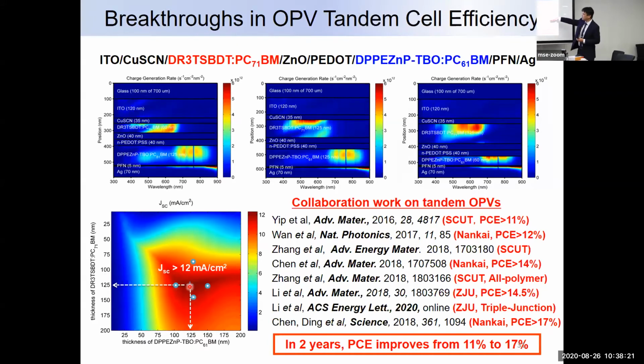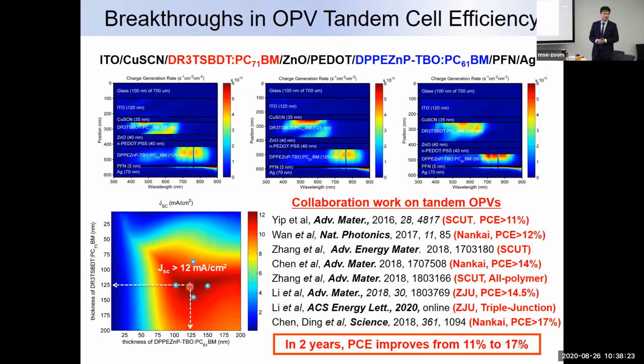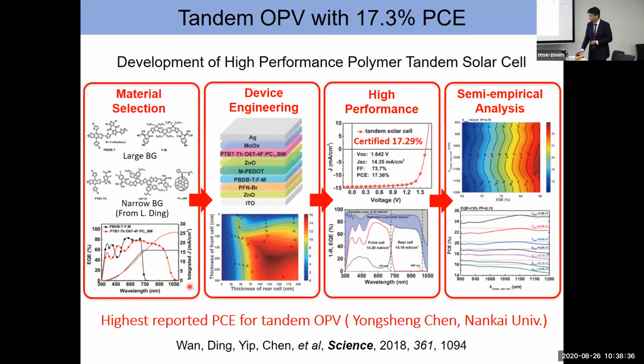We collaborate with a lot of groups working on this tandem solar cell, and about 2 years ago, we also published a paper in Science reporting one of the highest performance tandem solar cells at that time. So here is the work. You can see we have one layer that absorbs only the visible light, and the other layer absorbs the infrared light. When we couple them, we need to work on all-solution processing, which is not easy, but we found the right way to cast 6, 7 layers without destroying the bottom layer.